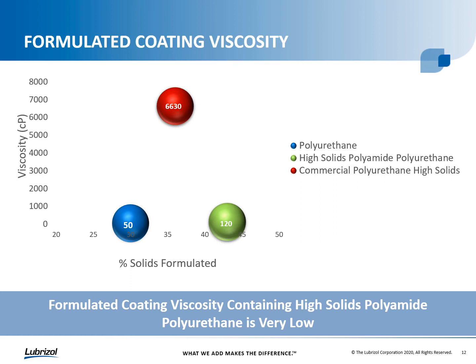Then we have the green bubble, which is the high solids polyamide polyurethane, formulated up over 40% solids, but yet at a very low viscosity of 120 centipoise. And then we have the commercial benchmark product, the red bubble up at the top of the chart. And so that's more formulated in the mid-30s range for solids, but you can see here significantly higher in viscosity at over 6,600 centipoise. And we'll see on the next slide how that high viscosity can impact the overall application and appearance properties.